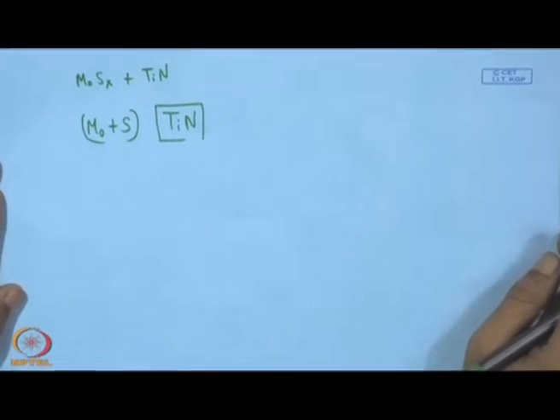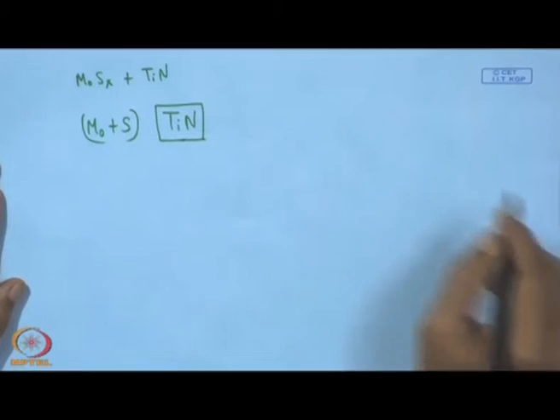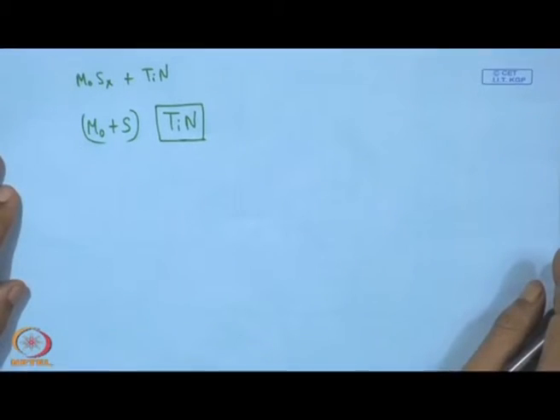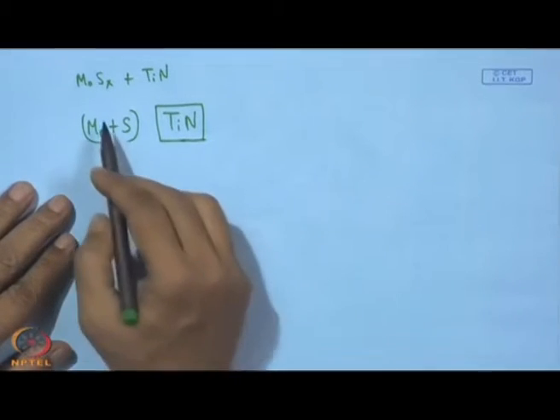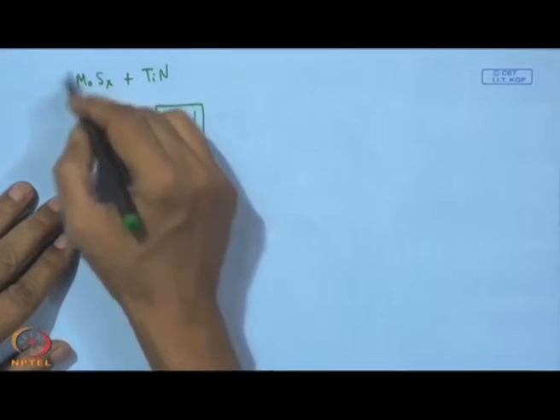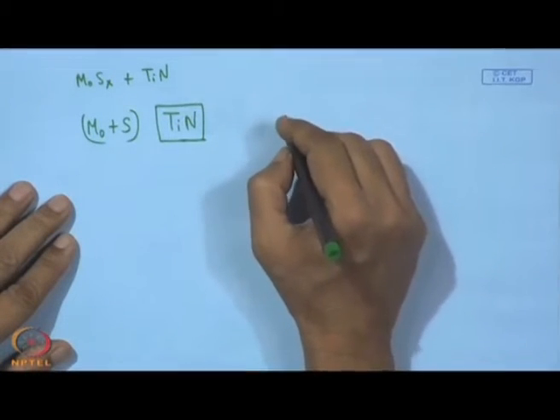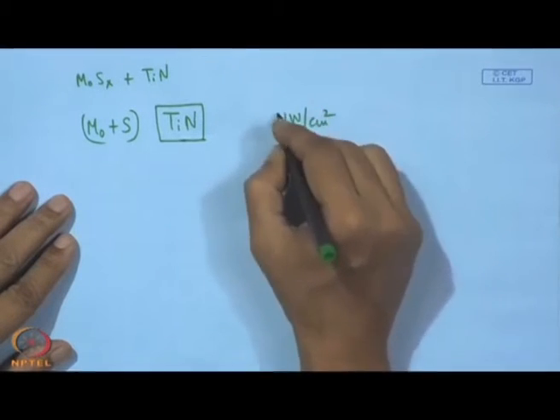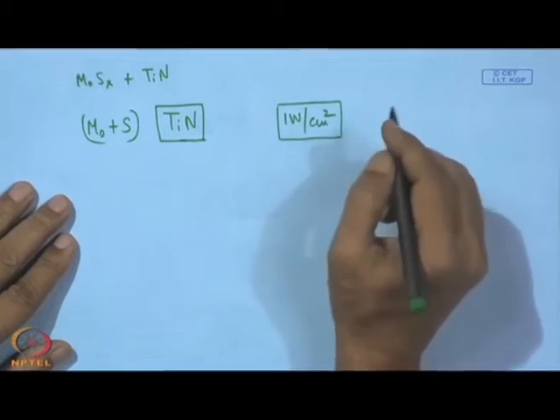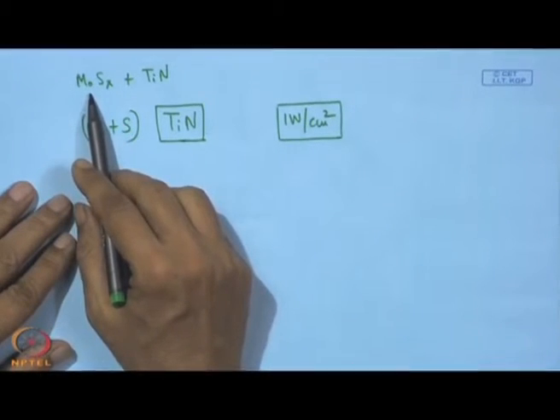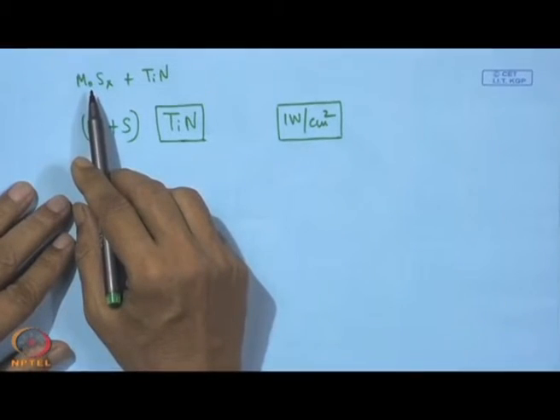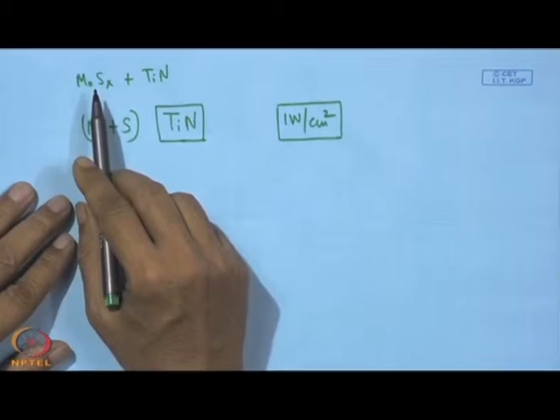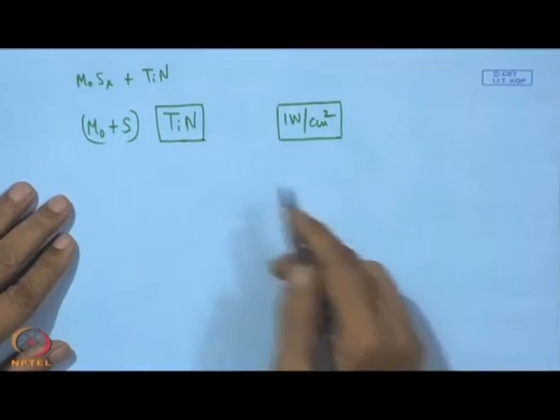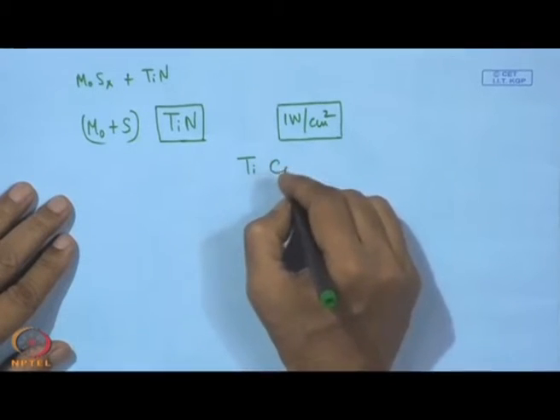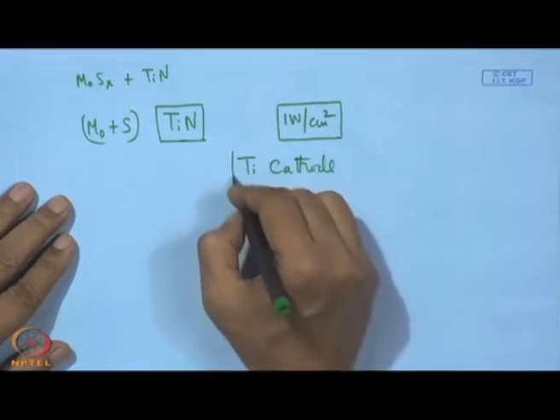So, this is something quite important and interesting to know, and for that what can be done? In this case, there is an operational restriction with the cathode power of the MoS2 target, say about 1 watt per centimeter square, and with this it may not be that easy to vary the cathode current for the MoS2 target. That means the molybdenum disulphide cathode current cannot be that conveniently varied. On the other hand, what can be handled rather easily is the titanium target, the titanium cathode current, and that has been done.